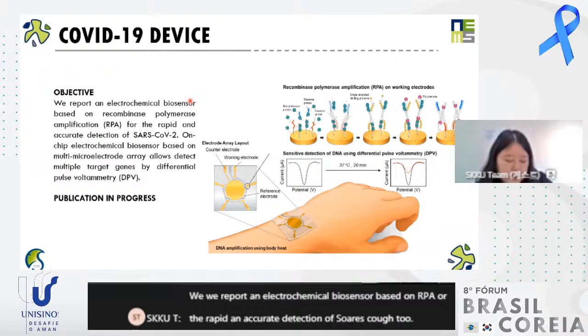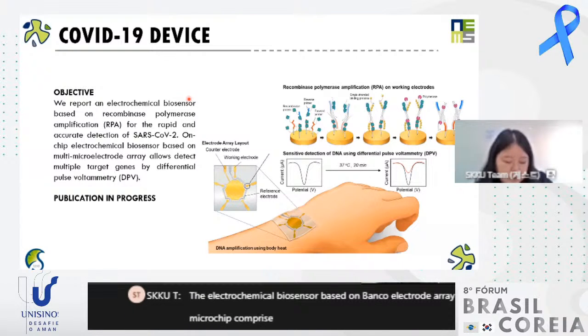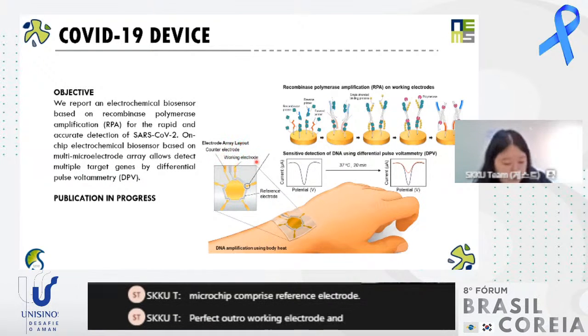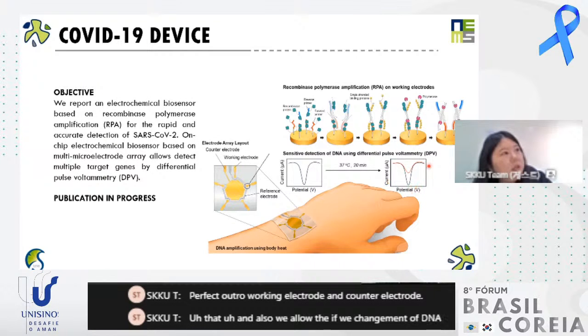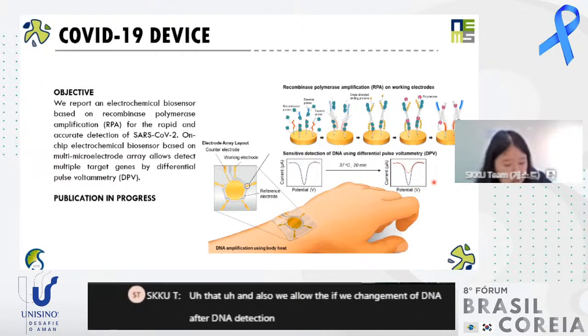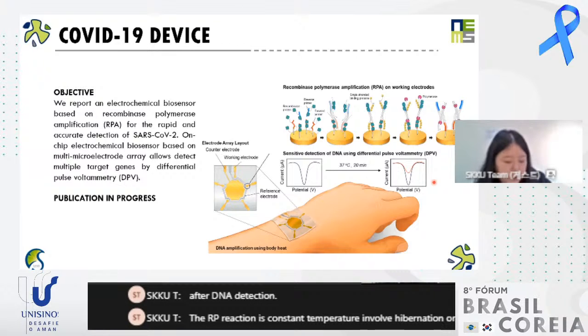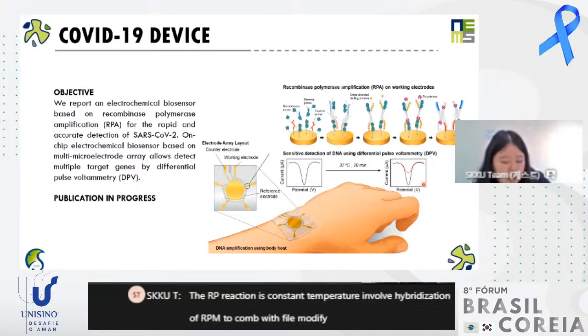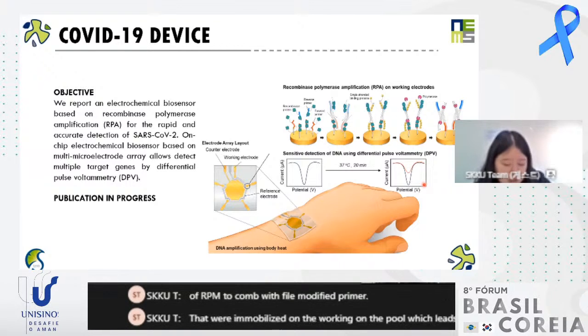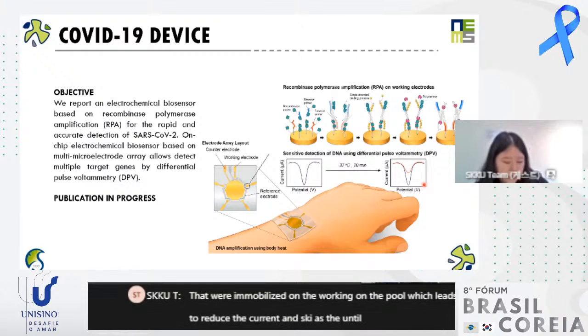The electrochemical biosensor, based on a microelectrode array microchip, comprises a reference electrode, working electrode, and counter electrode. We measure the DPV change of the DNA after DNA detection. The RPA reaction is at constant temperature and involves hybridization of the RPA amplicon with thiol-modified primer immobilized on the working electrode, which leads to reduced current density as the amplicon increases.